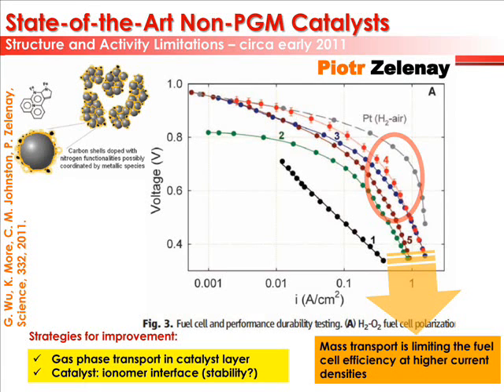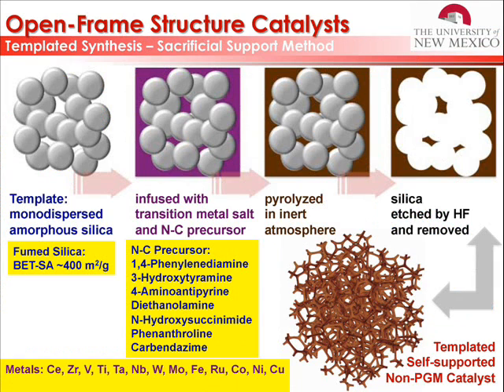So that limitation is overcome by our templating method, where we get silica, we make the catalyst around the silica, and then we extract the silica away. So in that way we have a non-supported or self-supported catalyst that consists only of the catalyst material. That allows you two things. One, you don't have support in the active mass, you have only active mass. So any spectroscopic method of studying that catalyst will give you information about the catalyst. You don't have support effect in recognition of what is active site and what is not. And then you have this open frame structure that allows for the transport.